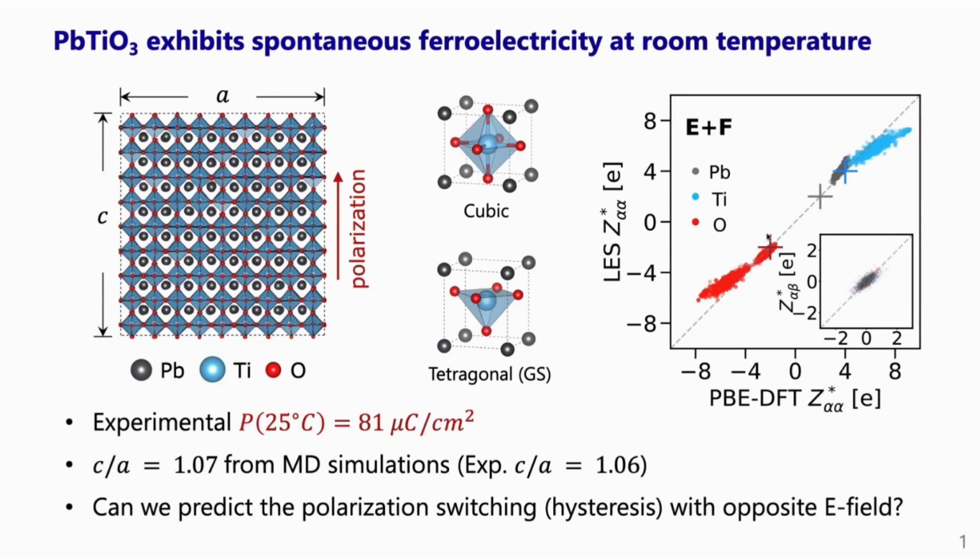You see that, for example, if you look at the Born effective charge of oxygen, the oxidation number of oxygen is -2. But you see the diagonal value of the Born effective charge actually massively exceeds that. So it has always been a little bit of a mystery in DFT why this is the case.